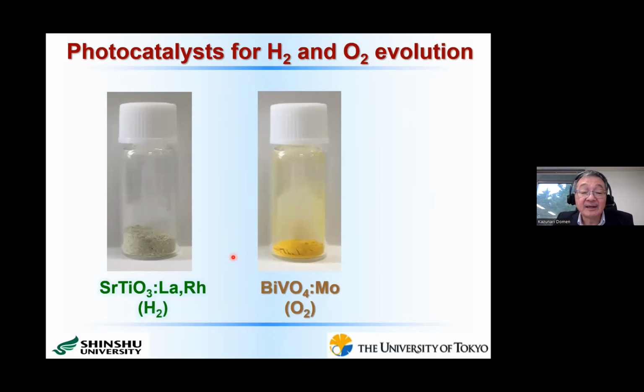In this case, we modified our photocatalyst a little more. We co-doped lanthanum and rhodium into strontium titanate to make a hydrogen evolution photocatalyst. For the oxygen evolution photocatalyst, we use molybdenum-doped bismuth vanadate. Although the color is somewhat different, if we measure by UV spectroscopy, the absorption edge in both cases is located at about 520 nanometers.